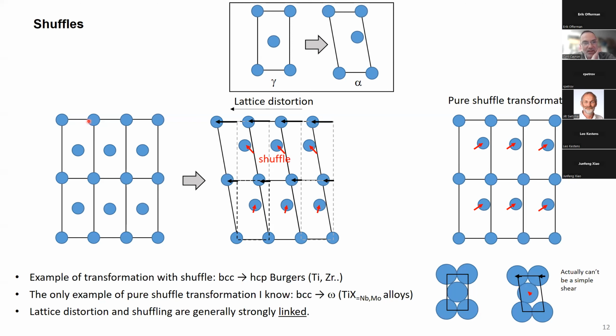Okay, so it means that for the atoms that are on the nodes of the lattice, it's just a simple shear. But for the atoms that were here in the center of the lattice, look, the trajectories of the atoms are quite strange. It is not a simple shear. So the trajectories of the atoms that do not follow the trajectory of the nodes of the lattice, we call them shuffling. And a well-known example of a transformation in which there is a shuffle is the BCC to HCP transformation in titanium or in zirconium.